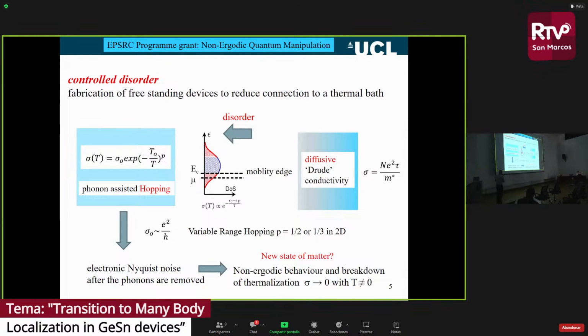T0 is a kind of the energy gap between the chemical potential and the mobility edge. But we've got this extra power here, P. Obviously, for the mobility edge, P is just 1 here. When we've got this phonon-assisted hopping, this exponential power here, P, changes. And depending on the type of hopping, it can be Mott. If it's Mott variable range hopping in 2 dimensions, the power here would be 1/3.